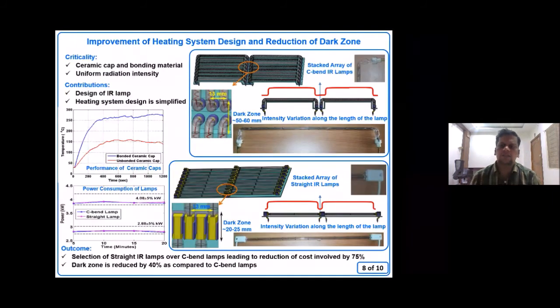Now another thing we have developed very recently is, whenever I assemble heaters one over the other with C-bend lamps, here you can see from here to this end I am getting almost uniform heat flux distribution, but from one end to the other end there may be a dip in the heat flux. This we call a dark zone. This dark zone for C-bend lamps is almost 50 to 60 mm.